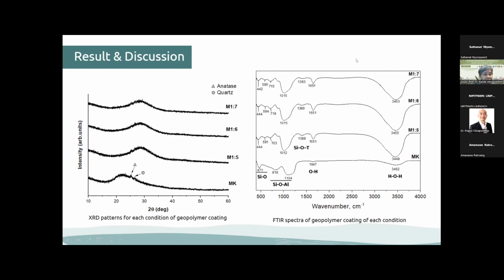After geopolymerization, the typical peak related to the asymmetric stretching showed the silicon-oxygen-T bond. The T means it could be either a silicon or aluminum bond, and this shows a difference from the base metakaolin. Due to the geopolymerization reaction, there was a noticeable change in the formulation in both aluminum and silicon, resulting in a new product with a different chemical environment than the metakaolin.